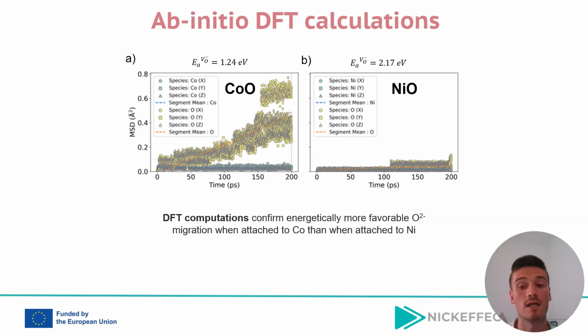To find the theoretical explanation to the dissimilar magnetogenic behavior of the compositionally different cobalt-nickel oxide disks, a combination of molecular dynamics, a universal machine learning interatomic potential, and DFT calculations was carried out.